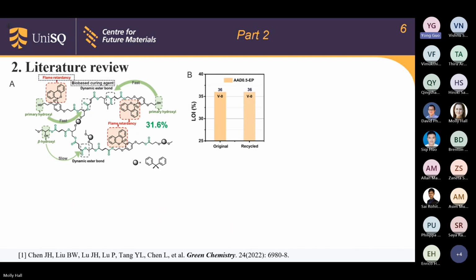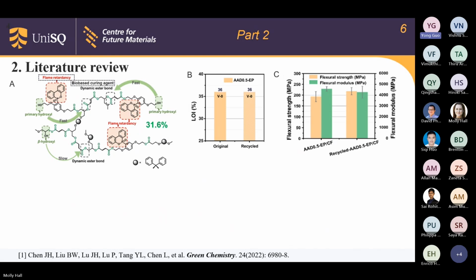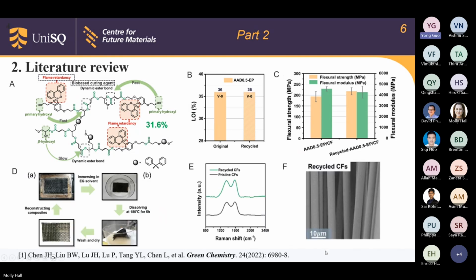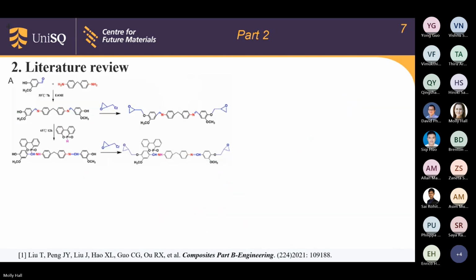First, the original and recyclable CF/EP both possessed excellent flame retardance with LOI of 36% and UL94 V-0 level. Second, it possessed excellent mechanical properties, such as flexural strength. And it achieved closed-loop recycling of the CF, and we can see from the Raman that the structure of the CF is retained, and from the SEM of the recycled CFs, the CF is very clean.